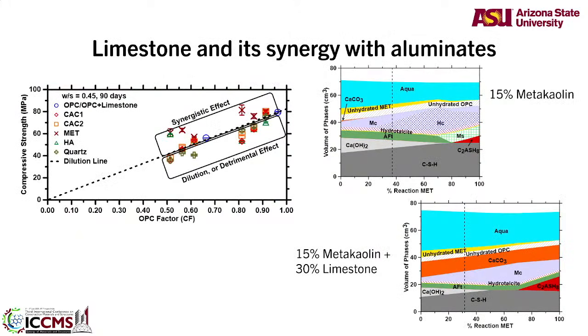Like I said, limestone is very good if you can make it react with some reactive aluminates. Cement has some aluminate, right? C3A. If you have ever looked at a mill certificate of cement, you will see something called tricalcium aluminate. So cement has some aluminate, which the carbonate can react with. Carbonate and aluminates, carboaluminates. Not much fancy naming there. You can form carboaluminates, and the carboaluminates can increase your strength a little bit. You can increase your solid formation, solid products, increase your strength.